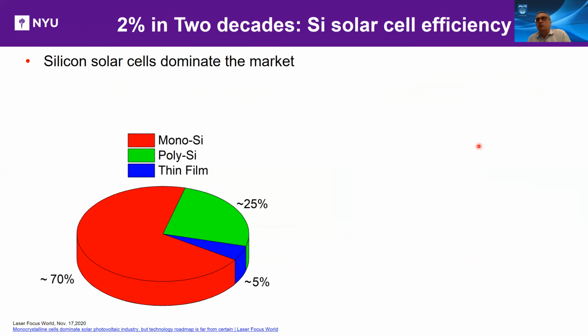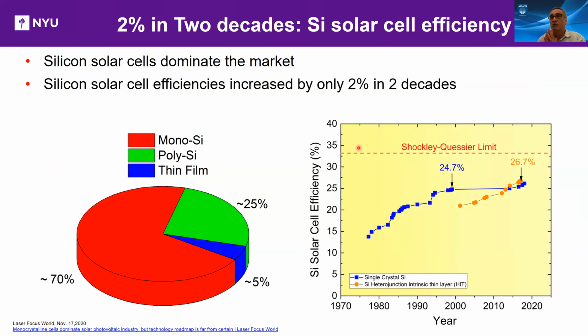So the silicon solar cell efficiency, even though we've made a lot of strides in reducing the levelized cost of electricity, has actually stalled, and that has ramifications for the module efficiencies. Silicon solar cells dominate the market, so it makes sense to work on them and technologies that might help them. The reason it has stalled is because the efficiencies are approaching a fundamental limit called the Shockley-Queisser limit. If you're not familiar with that limit, I will explain the nature of it. And in fact, what I'm going to describe to you is trying to surpass that natural limit.